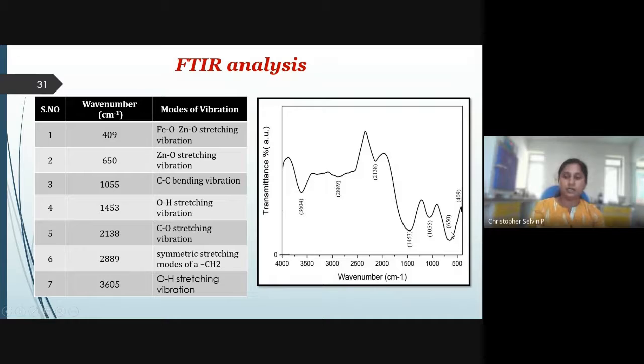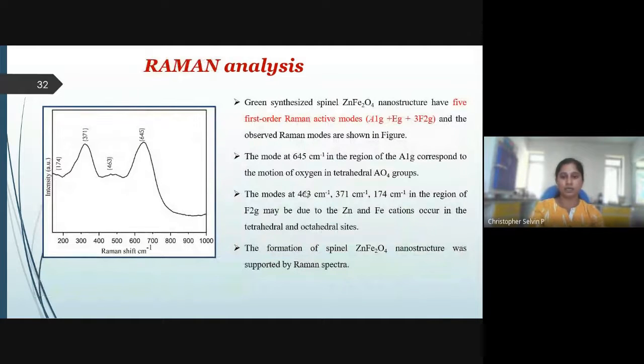Comparatively, the metal oxide region is highly intense in this material, so we can say that a small interaction of this may not impact the electrochemical results of this material. Anyhow, we can incorporate these results if we see any changes in the CV patterns. Followed by that, we have Raman analysis.